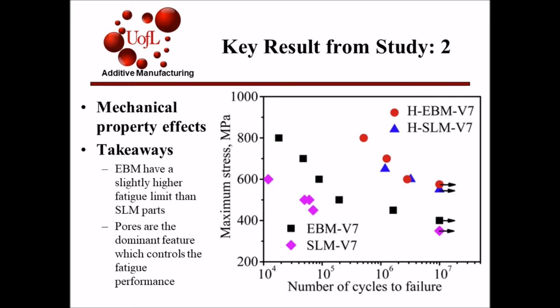The illustration on the right shows the stress versus number of cycles to failure data for the samples fabricated by EBM and SLM processes in the vertical orientation. Key takeaways from the data was that EBM have a slightly higher fatigue limit than the SLM parts, with EBM parts being shown in the black and red and SLM in purple and blue.